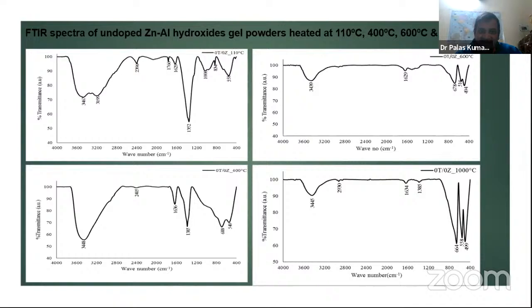temperature. And with increasing temperature, especially at 1000 degrees centigrade, there are very intense absorption peaks between 500 to 700 centimeter inverse, which essentially indicates the Zn-O-Al bond, which directly and indirectly shows that there is a formation of zinc aluminate at this temperature.